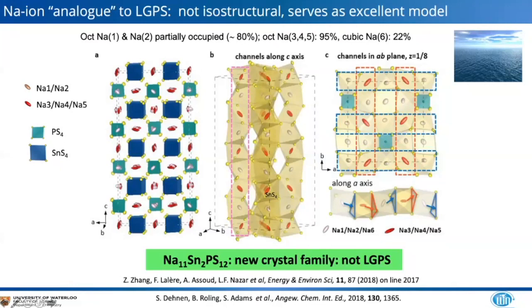And it has ordered PS4 and SnS4 tetrahedra shown here in teal and in cobalt blue. And it has channels which contain different sodium ions. There's actually six sodium ion sites in this material. And these form channels that run along the C-axis and also along the A and the B axis. So it's a three-dimensionally conductive material. You can see that these channels are formed by face-sharing octahedra of the sodium that run in all of those three directions. And here's a better depiction of that along the A axis, where you can see the triangular window through which the sodium ions pass.